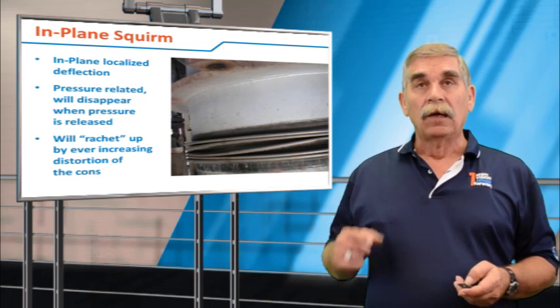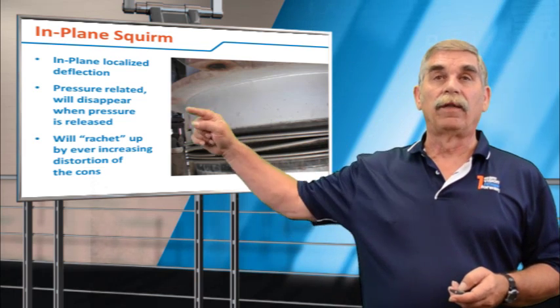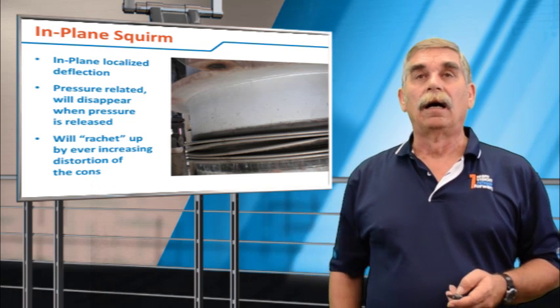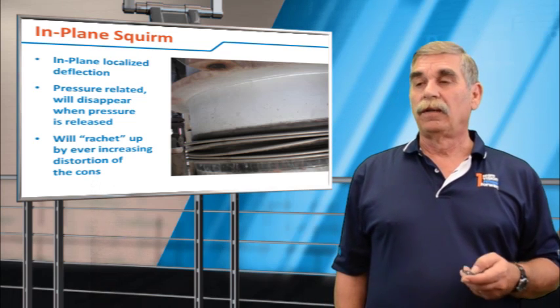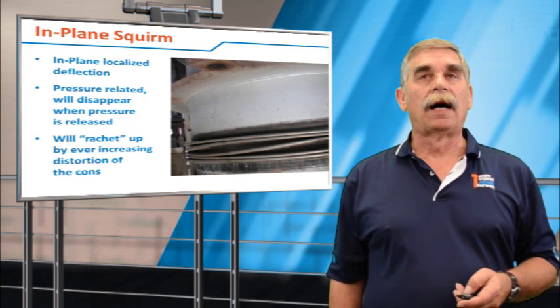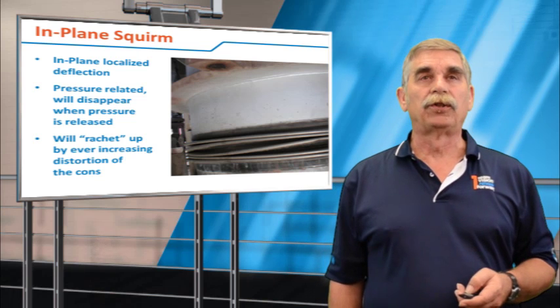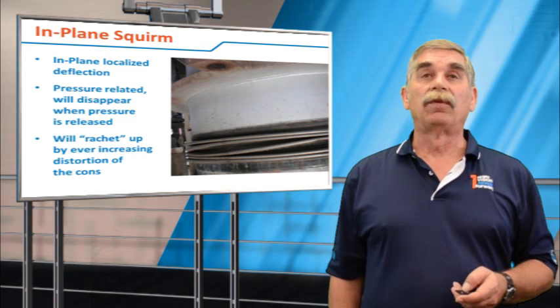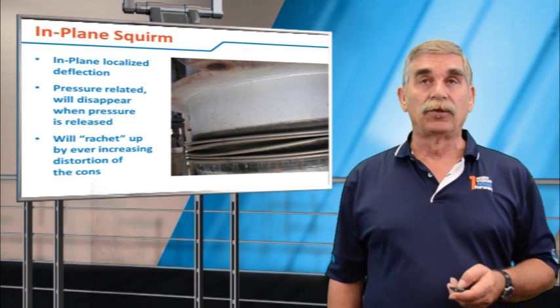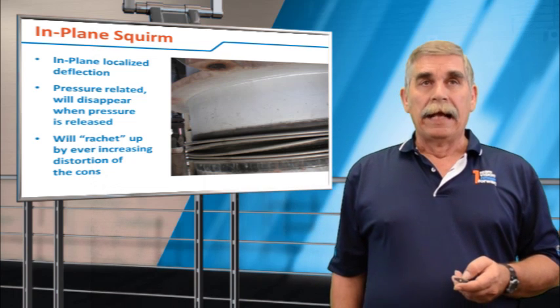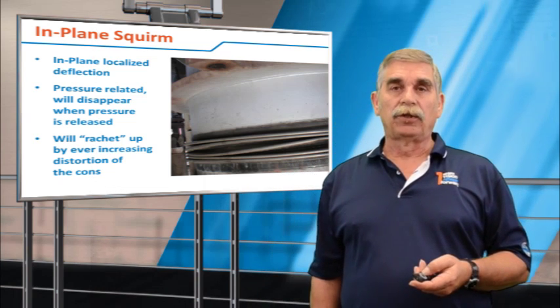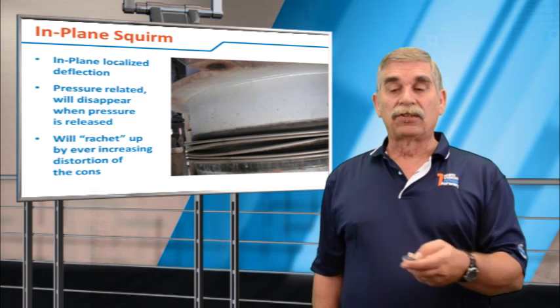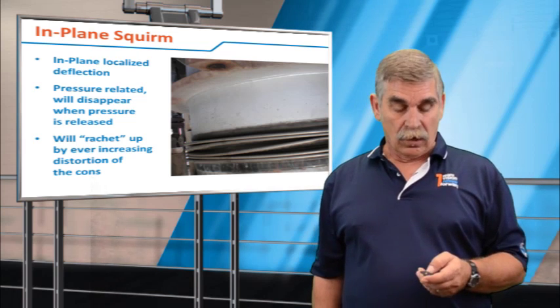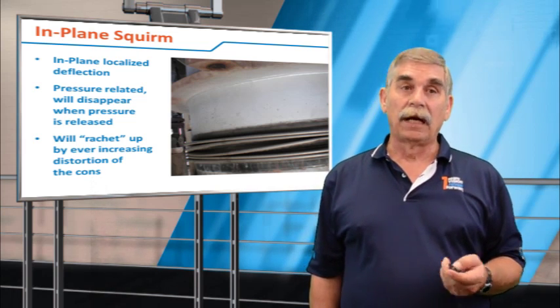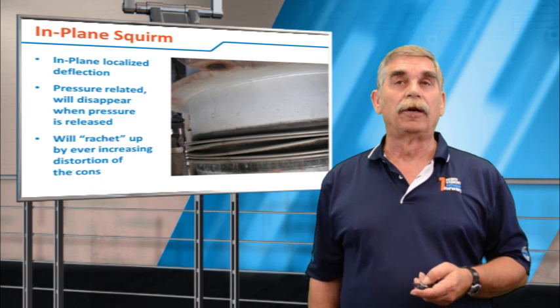The next type of squirm is in-plane squirm, where the convolutions will take on this wavy appearance. This occurs when the convolution height is too high for the given pressure, and the convolution will actually start to become unstable. It's pressure related, and you will only see it when the bellows is under pressure. So if the bellows is insulated or has a heavy cover, you'll probably never see this because you'd have to take that off to see it under pressure.